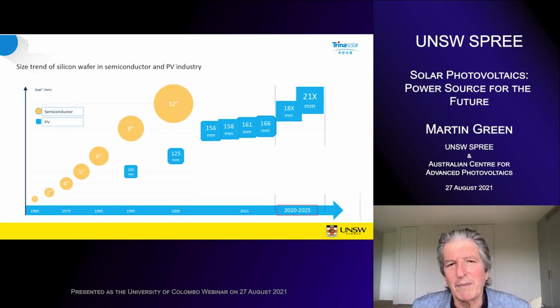For a long time, the solar industry used smaller wafers than microelectronics. This graph here, the yellow, just shows a timeline for the uptake of wafer size in microelectronics. The industry went to 12-inch or 300 millimeter diameter wafers around the turn of this century, whereas the solar industry stayed with much smaller diameter wafers, largely due to the high current output of the cells. Handling more than 10 amps from a cell that size produces challenges with resistive losses within the module and external to it.